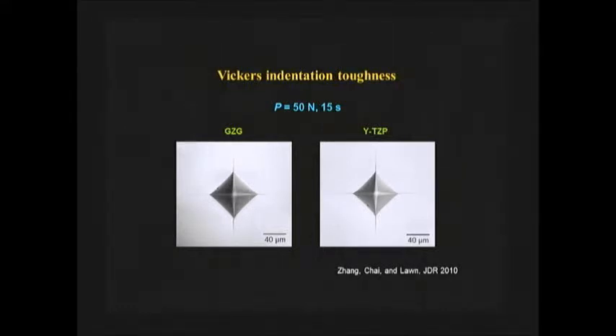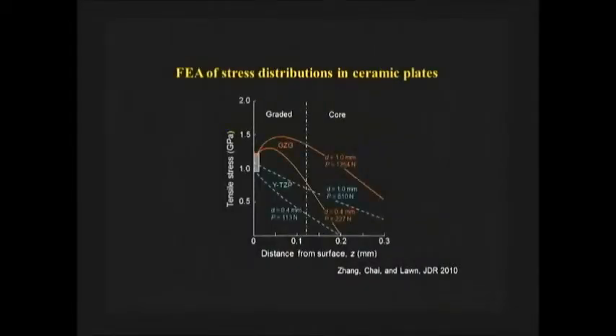and how tough the material is, resistance to crack propagation. So it's very similar in this case, resistance to crack propagation in this case. And in fact, we did a finite element analysis on these materials. The red curves here showing graded structures. Here is 1 millimeter thick, and this one 0.4 millimeter thick, versus ungraded, which is blue curves, 0.4 millimeter and 1 millimeter. What this one shows us is the tensile stress in the material when the plates are in flexure, and the bottom surface, the lower surface of the material.